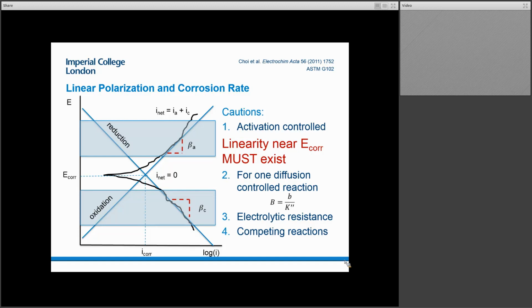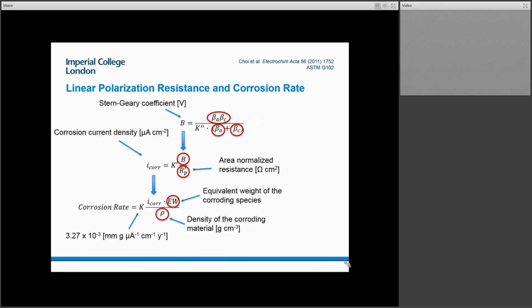But moreover, you might say, okay, well, I have linearity near the corrosion potential, so I must have kinetic control. So the other caveat is that you need to be quite careful that this sort of derivation also doesn't account for such issues as electrolytic resistance. But moreover, it also doesn't deal with competing reactions. So we're assuming a very, very simple system. And so my intention is not to put you off, but is to make sure that if you're using this technique, you're thinking very, very carefully about the kinetics and the mass transfer of your system, but also about what reactions might be happening and what assumptions you might be making.